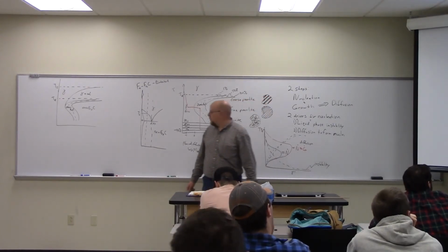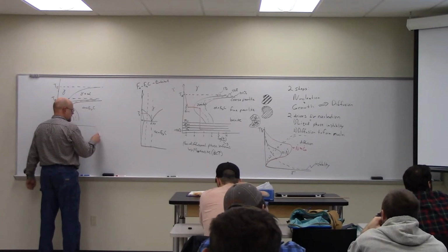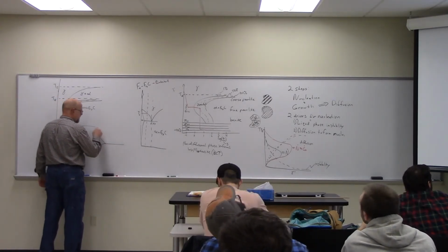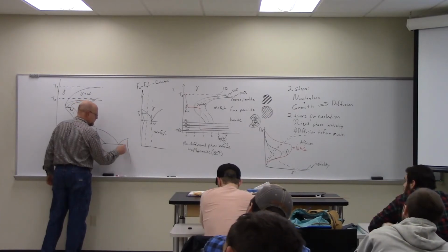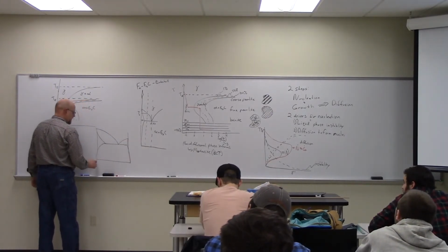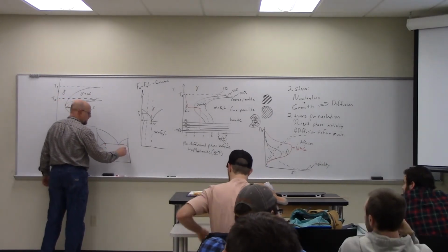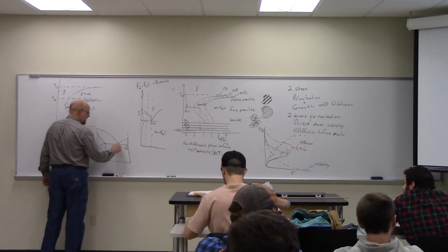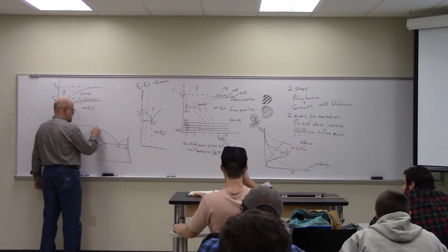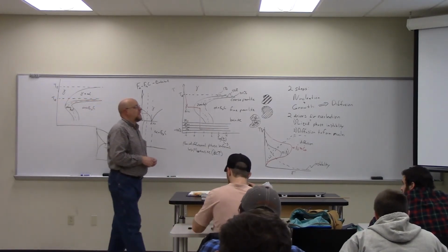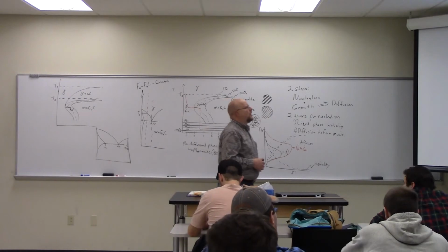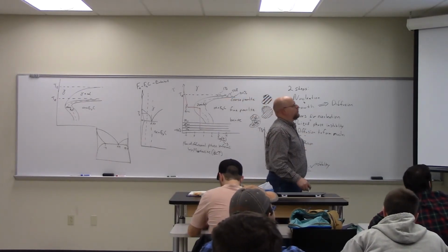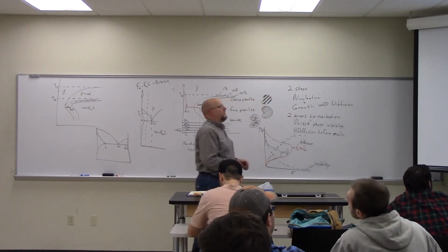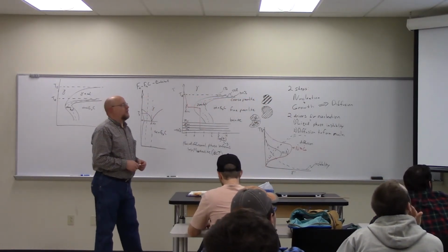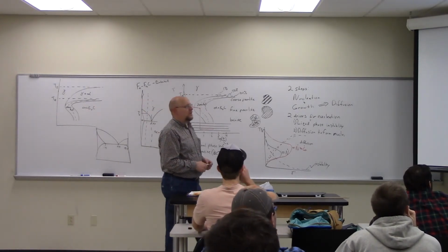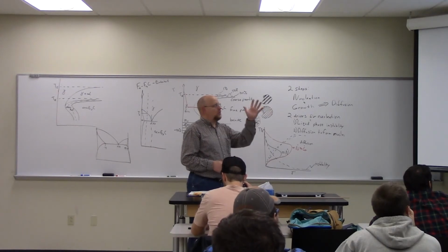All right, so we're back to the lead tin diagram. Probably should have put the lead tin diagram up there. Hopefully by this point you guys are pretty familiar with this. This is 19, this is 97.5, this is 61.9, and the temperatures we're going to have to deal with. Given precipitation rates of 3.7 times 10 to the third per second, and 1.4 times 10 to the third per second at 20 degrees and 0 degrees. So that's the rate at which precipitation occurs.